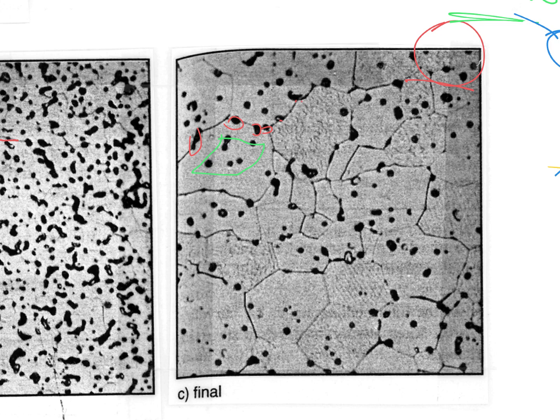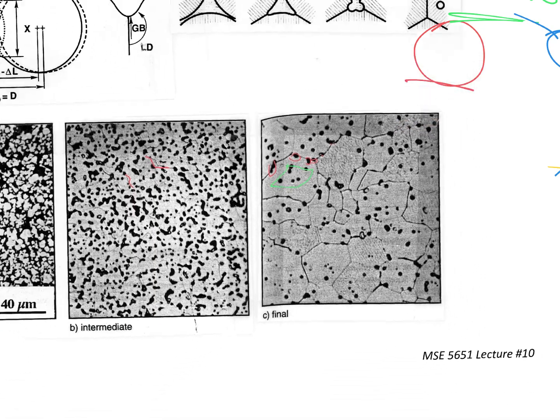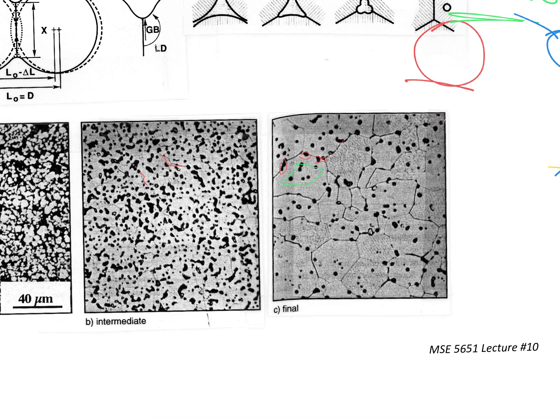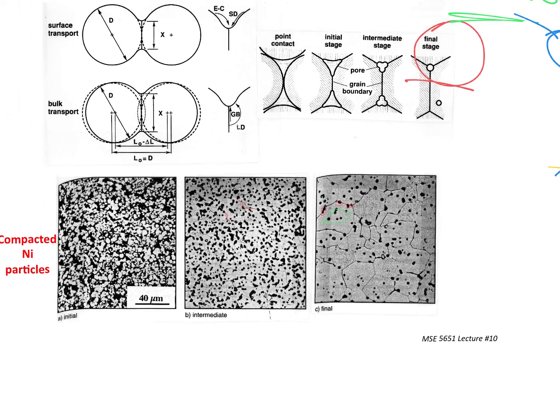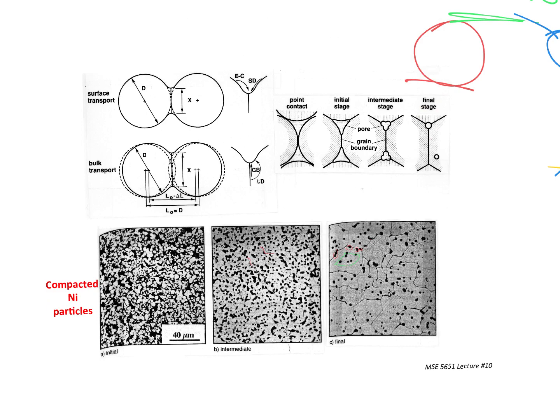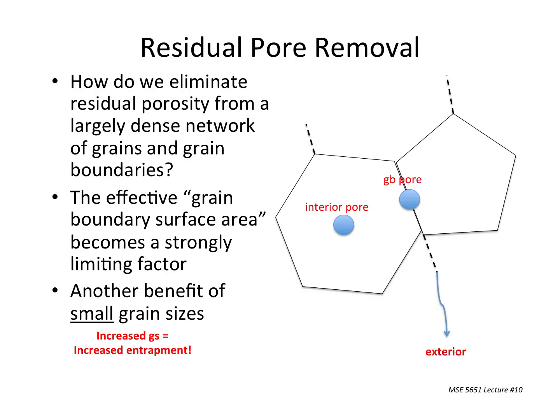Okay, so you want grain boundary surface area, is what they call it. If you took this thing and blew it up into all the different grains, you'd have a certain surface area associated with that collection of grains. And you want that to be as high as possible, meaning that you want the grains to be as small as possible, so you have as many pathways to the surface as possible, so you can get the best densification you can possibly get. All right? And the whole process of grain growth frustrates that because it gets rid of grain boundary surface area. It eliminates it, all in a pursuit of minimizing gamma GB. Okay? All right, and that is the way it is. The system does that. We know how to slow it down, but in many cases we can't stop it.